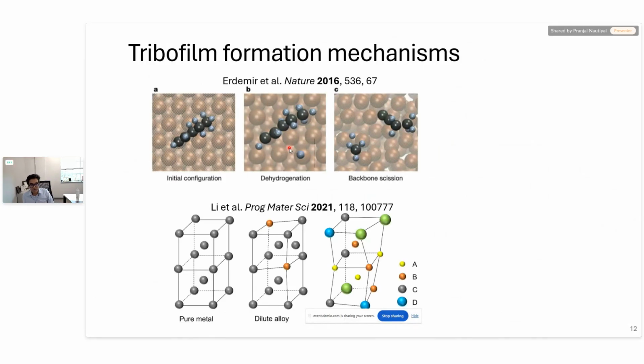In high entropy alloys, in our case nickel, cobalt, chrome, a medium entropy alloy, the presence of multiple principal elements in the lattice provides enhanced catalytic activity. And I'm illustrating this through the schematic here. In pure metals, you have elements of the same size occupying lattice sites. The lattice is very happy. There is less distortion in the lattice. Similarly, in dilute alloys, there are few solute atoms, and that causes some distortion, but not a lot. But in multi-principal component alloys, the presence of multiple elements in lattice sites causes a lot of distortion.